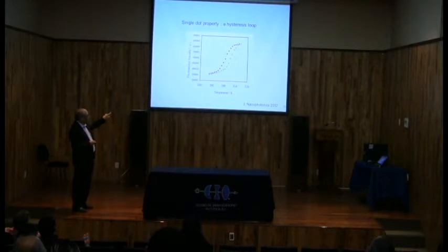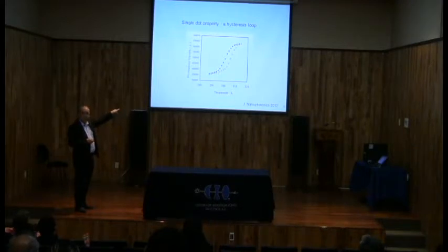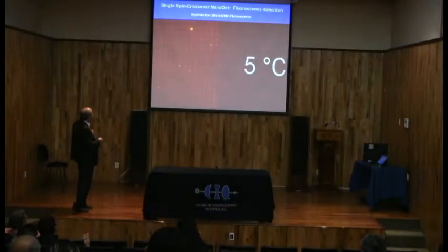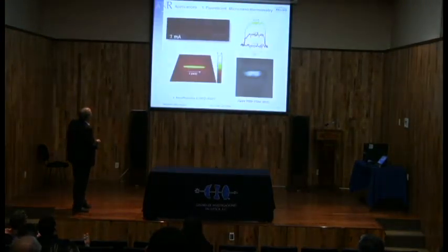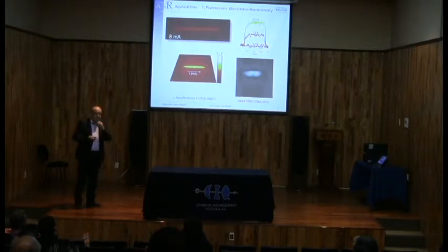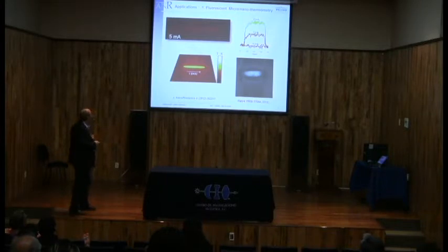This is not the right curve of the dots, but the curve of one dot is something similar to this one, where we have shown also that in one dot you can have the spin crossover through the analysis of the luminescence, and you still have the hysteresis loop. Okay, so now of course you can guess that there are many applications using this effect. For example, in nano thermometry devices.